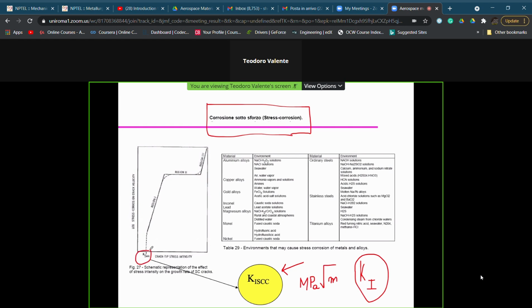The possibility to use this design guideline in order to avoid stress corrosion cracking depends obviously on the absolute value of the K1SCC, because if this is very low, some units of megapascal square root meter, well, it cannot be used. If it is too low, it is as to say, in order to avoid stress corrosion cracking, let's keep our tensile stress to a very low value. That's very simple, but not usable in an engineering approach. So if the value of the K1SCC allows us to avoid stress corrosion cracking by taking the K1 value lower than K1SCC, that's fine.